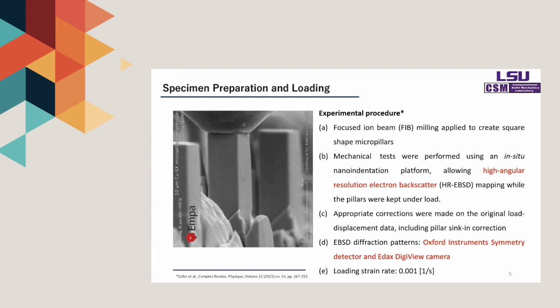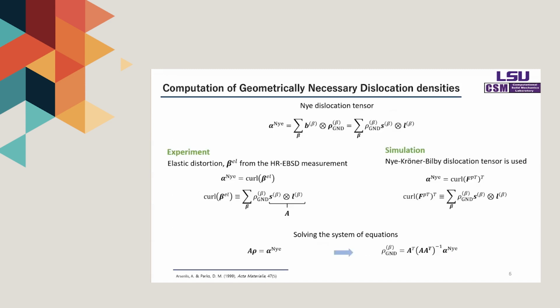EBSD diffraction patterns were recorded during the mechanical test to achieve mapping of the GND population. To estimate the GND densities experimentally, the elastic distortion is captured by the high angular resolution electron backscatter diffraction technique, and it can be solved by the inversion method.